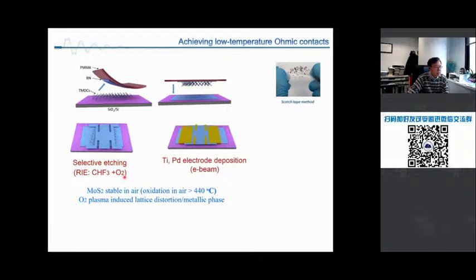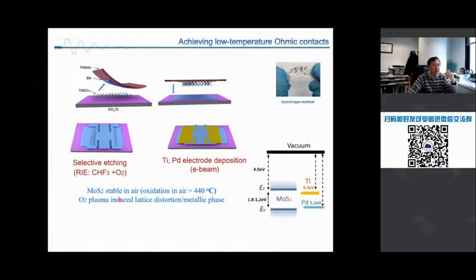Molybdenum disulfide is pretty stable in air. So we use oxygen plasma to quickly make the window through the boron nitride and then cause the phase transition. I'll show you the details.